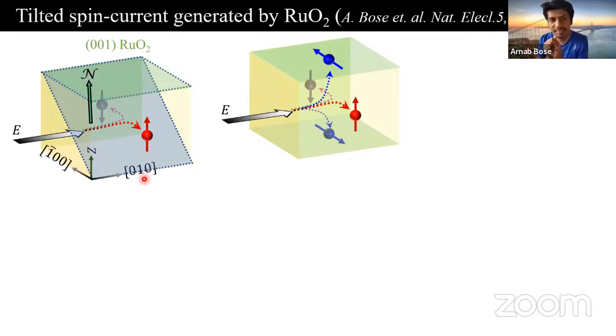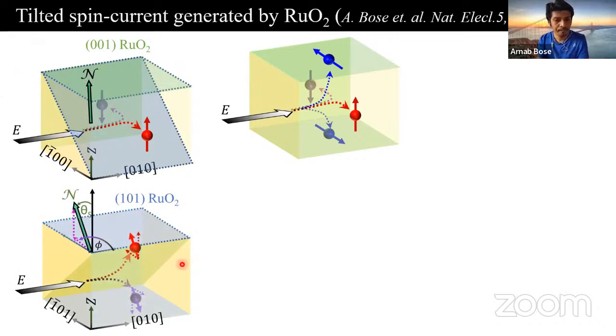But the question is, experimentally, how do we distinguish it? So we found that for the 001 plane, it is difficult to distinguish. But if you work on a different plane, which is 101, then we'll be able to distinguish it. For example, this is the 101 plane, and this shaded area is the 001 plane. And we can do a coordinate rotation and get from this configuration to this by taking a rotation along the y axis. And because of this rotation, we immediately find that the generated spins will be tilted. So this is something really different that should happen for ruthenium dioxide due to the spin split bands, distinctly different from the regular spin Hall effect. So this is what we want to experimentally detect.